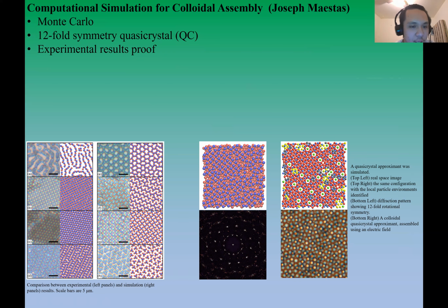And these structures have all been confirmed by our experimental results, which means the simulation in our group is highly consistent with our experimental results. On the right-hand side, he also found that under different confinement between the substrates, colloidal particles can form a quasicrystal, which is not commonly seen in natural life.